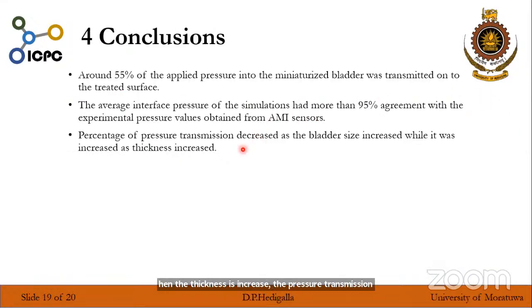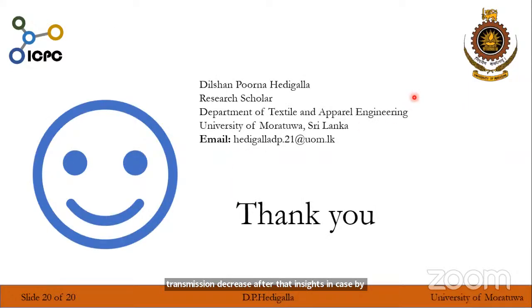Around 55% of the applied pressure is transmitted onto the treated surface, and the average pressure of the simulation had more than 95% agreement with the experimental results value obtained from the AMI sensors, and the percentage of pressure transmission decreased as the bladder size increased, while it increased as the thickness increased. Thank you.